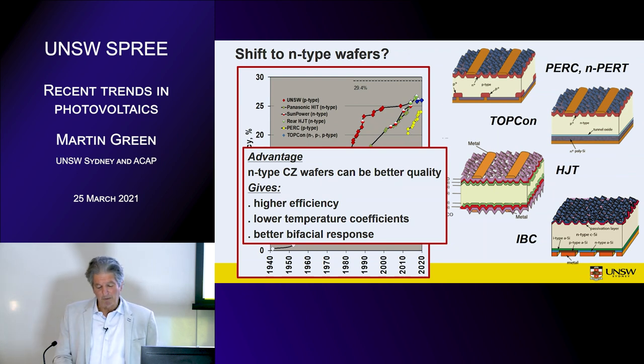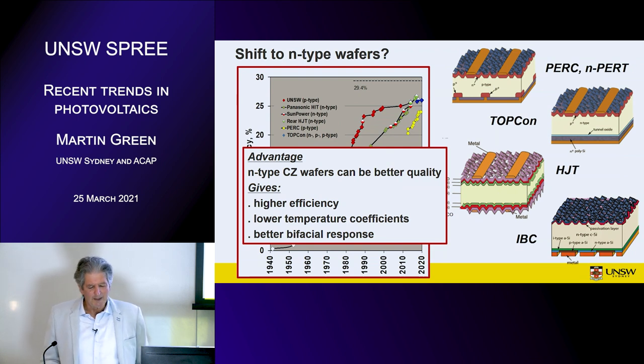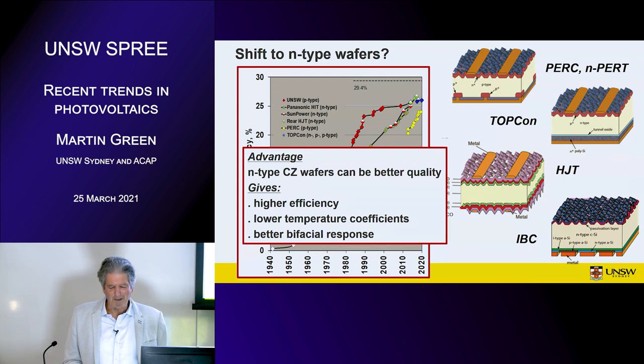So the advantage of going to N-type, the thing I should mention is that the PERC and the TOPCon are quite rugged technologies in that they can tolerate material that isn't perfect because you just lose a bit of current, and neither of them is as high voltage as a heterojunction, for example. So you might lose a bit of current, perhaps a little bit of voltage. But with the heterojunction, the advantage only comes through voltage. So you need a high open circuit voltage to get the efficiency advantage, because the current gets reduced by the absorption in the ITO, which is a transparent conducting semiconductor, and the amorphous silicon, which is made very thin to decrease the absorption, but it still absorbs a bit. So you're always going to have lower current from a heterojunction than from a PERC or TOPCon.